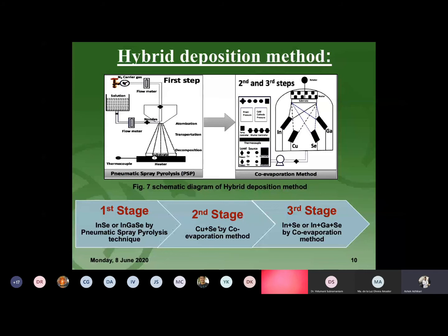Finally, in the third stage, indium selenide or indium gallium selenide were incorporated in order to get a slightly copper-poor composition. This slightly copper-poor composition with excess selenium gives the p-type absorber layer, which is necessary in our work to achieve efficiency.